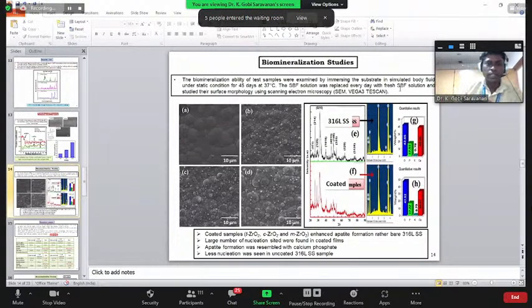After 1.5 months, we took the same morphology. You see a lot of grains, so nucleation growth has happened. This is an uncoated one. Compared to the uncoated one, all the coated materials show a lot of nucleation sites. It indicates that the coated material possesses a more bioactive nature than the uncoated one.